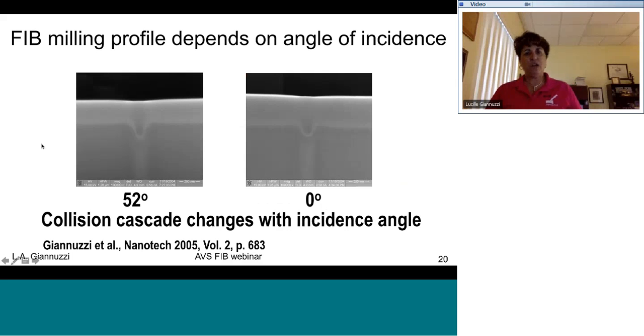The milling profile will also, of course, depend on your incident angle, which is directly dependent on your ion-solid interaction. So if you FIB mill at 52 degrees versus 0 degrees incident angle, obviously this is going to affect the range and also your ion-solid interaction, so you'll actually develop a deeper cut, for example, at 52 degrees versus 0 degrees.